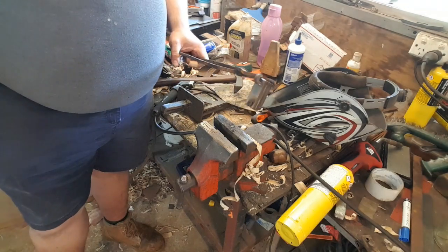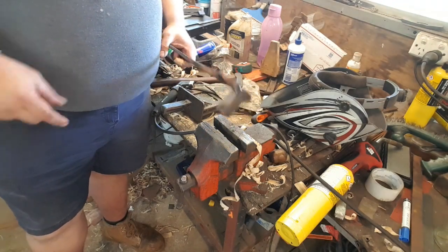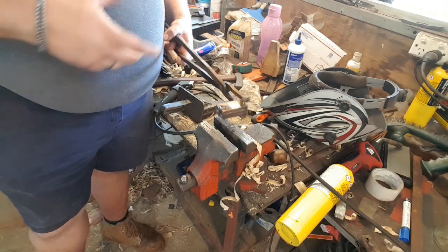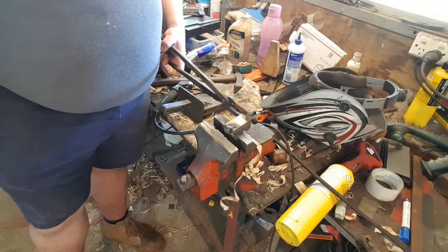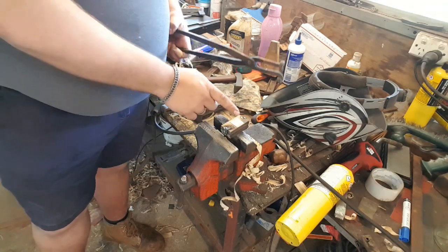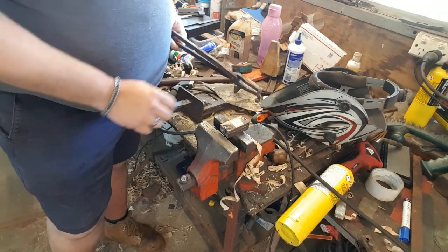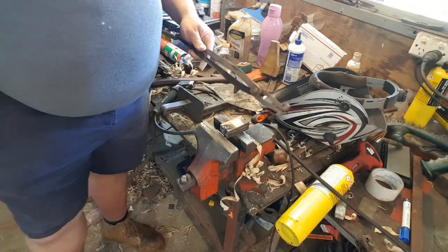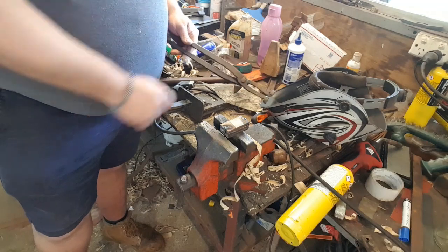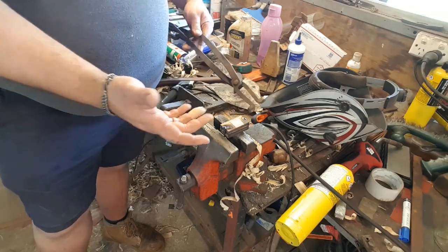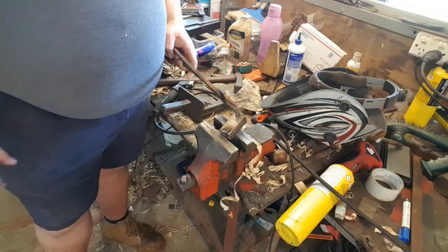That being said, if you do that, you're going to have an issue with holding onto it. What I would recommend is leaving one piece of the material, normally in the middle, much longer so that you can grasp that with tongs outside the billet. In this case, I don't need to do that because I can weld a handle on, so that's what I'm going to do now.